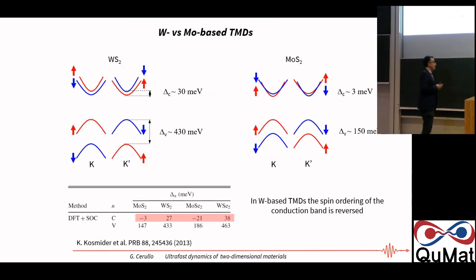Now, let me go back to this issue that the valence and the conduction band have spin-orbit interaction, spin-orbit coupling. So they are split. There's a strong splitting in the valence band and a smaller splitting, almost negligible, one order of magnitude smaller or even less in the conduction band. But what is very interesting is that if we look at these two materials, we see that there is